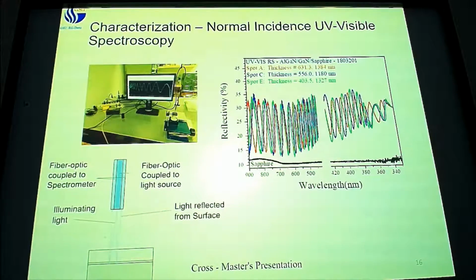Basically, as we change the wavelength, the intensity of the reflected light increases and decreases, and we can correlate that to the thickness of the material. A nice thing about it is that where these fringes stop is where the band gap is. So we can actually directly measure the band gap of the material at the same time. Now, that being said, this is only from about 200 to 900 or 1,000 nanometers. Indium nitride has a band gap of 0.6 eV, so that's much lower energy. That's all the way off on this side of the graph. So we can't actually measure the direct band gap of indium nitride using this machine.